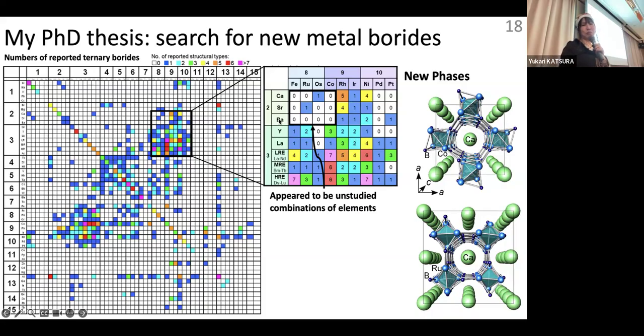So these are the combinations of the group 2 and group 3 elements combined with the group 8, 9, 10 transition metals. These are very popular, but the group 2 ones are not so popular. This may be because the synthesis was a bit difficult. These elements are reactive, so they react with the quartz glass, so we have to seal this in metal tubes to avoid the reaction with the quartz tube.